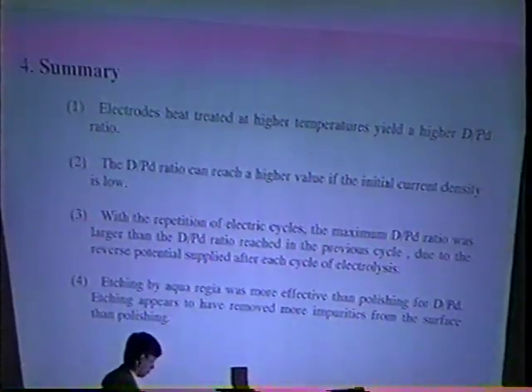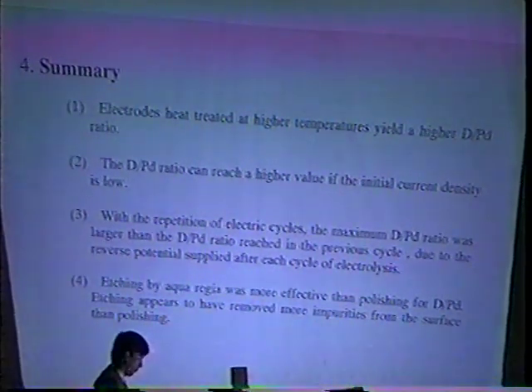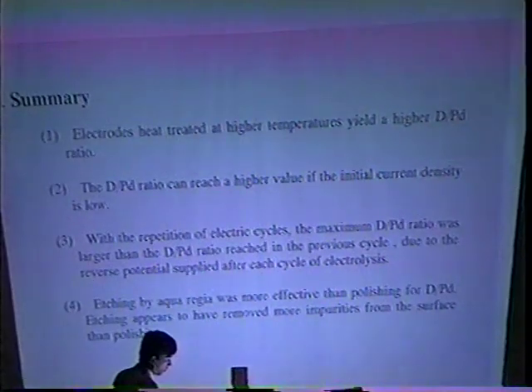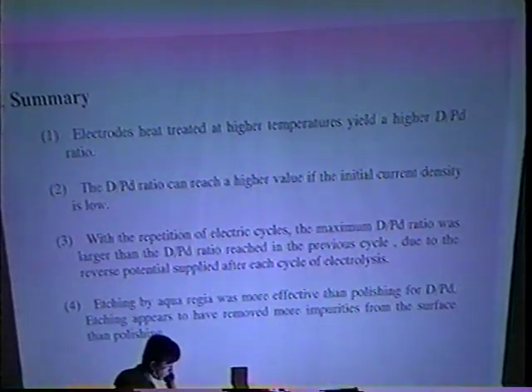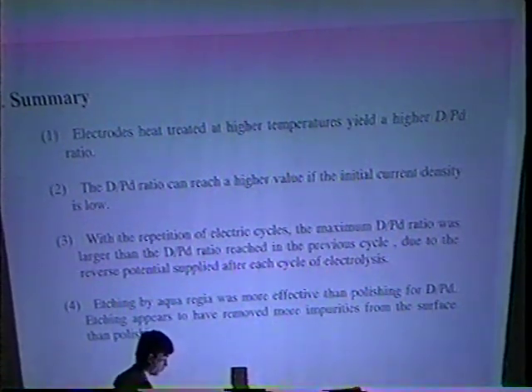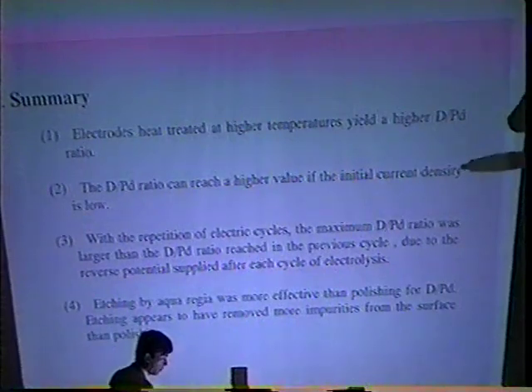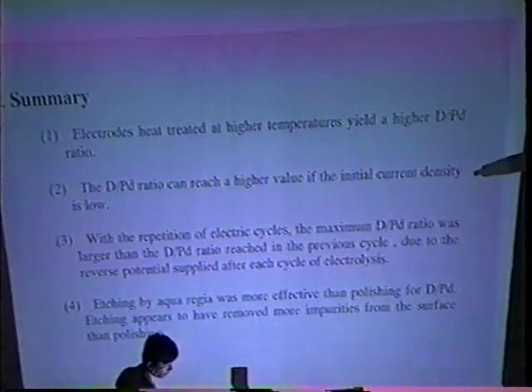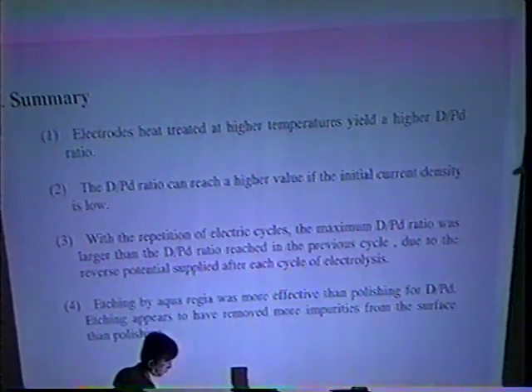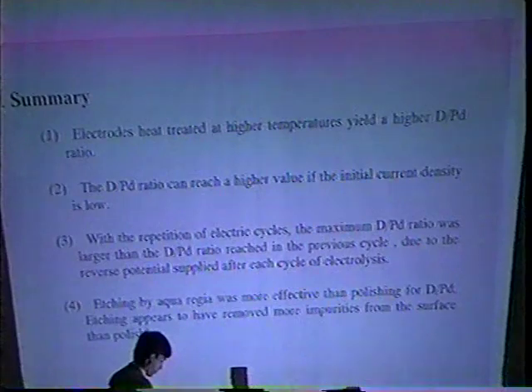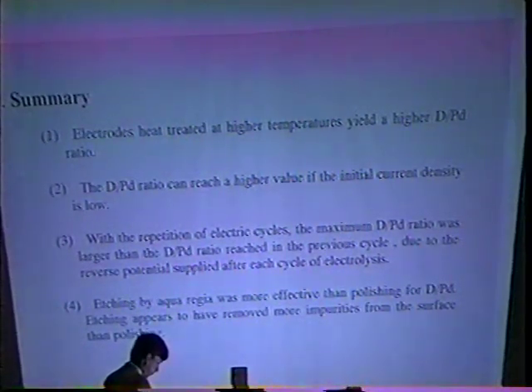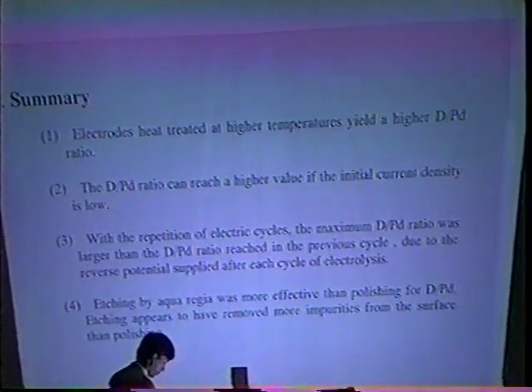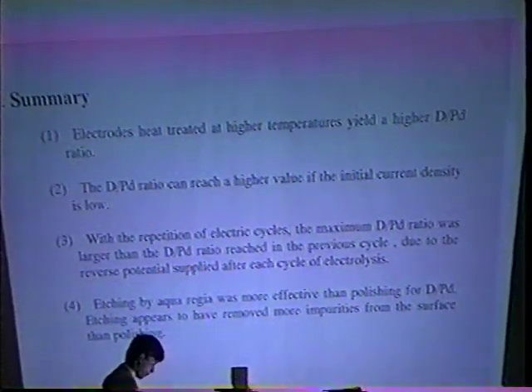There are several conclusions based upon the results of this study. Cathodes heat treated at higher temperature yield a higher D/Pd ratio. The D/Pd ratio can reach a higher value if the initial current density is low. The repetition of the electric cycle results in a higher D/Pd ratio than that reached in the previous cycle. Etching with aqua regia was more effective than polishing for D/Pd.